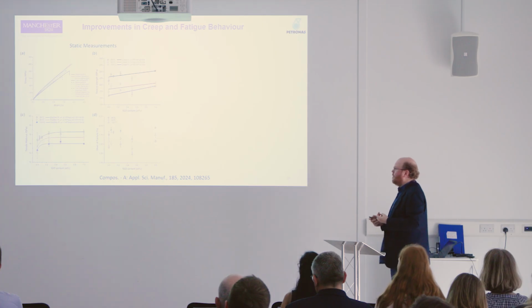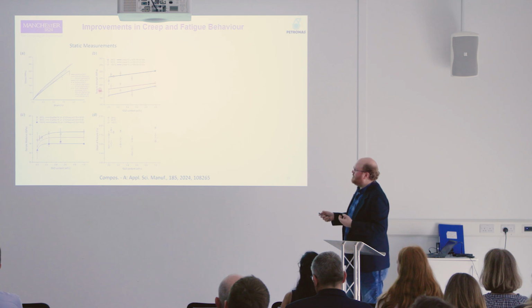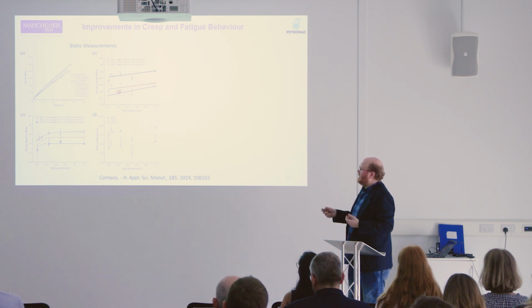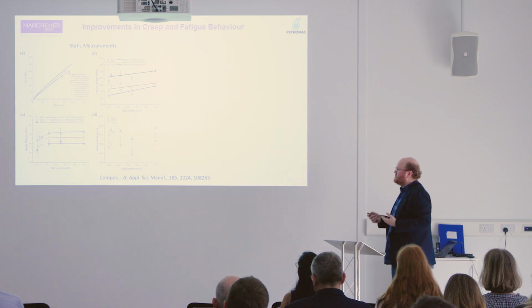We were looking at glass fiber composites with functionalized graphene. So again, this is looking at how, as we functionalize the material, we can improve the performance or the interaction with the matrix. This was amine functionalized graphene in an epoxy, so you get a sort of chemical interaction between those materials. It was spray coated on like in our other cases, so you can control the dispersion. And what we find, this is the static measurements, is what you'd expect to see: as you increase the content up to, say, 1%, you get a more or less linear increase in the tensile strength and the modulus up to a certain level, and then it flattens out.